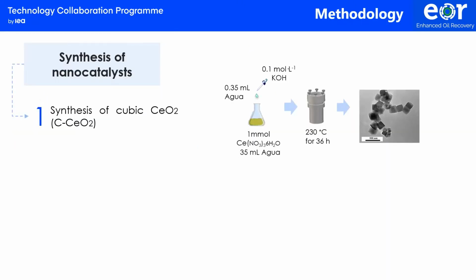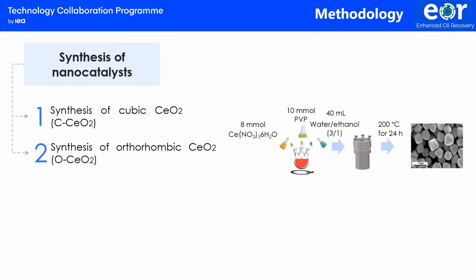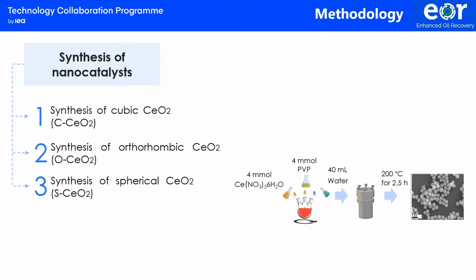In this research, 3 different nanoparticles with cubic, orthorhombic, and spherical morphologies were successfully synthesized by a simple hydrothermal method. The cubic nanoparticles were synthesized using potassium hydroxide and a cerium nitrate hexahydrate salt precursor. The orthorhombic nanoparticles were synthesized using the same salt precursor and a polymer, PVP, in a water-ethanol solution. Finally, the spherical nanoparticles were synthesized using the same salt precursor and the polymer in a solution with only water.